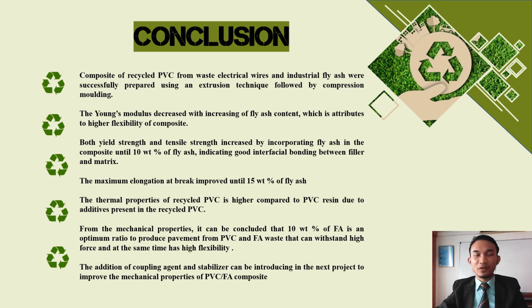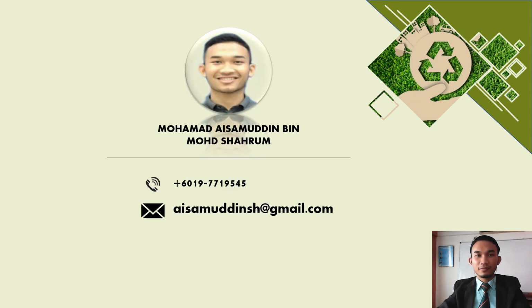The thermal properties of recycled PVC are higher compared to the PVC resin due to the additives present in the recycled PVC. From the mechanical properties, it can be concluded that 10 weight percentage of fly ash is an optimum ratio to produce pavement from PVC and fly ash waste that can withstand high force and at the same time has high flexibility. The addition of coupling agent and stabilizer can be introduced in the next project to improve the mechanical properties of PVC and fly ash composite. That's all from me.